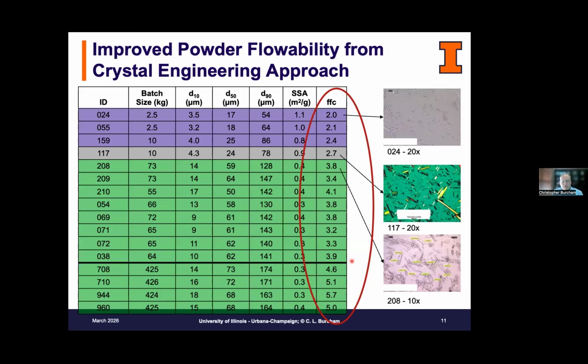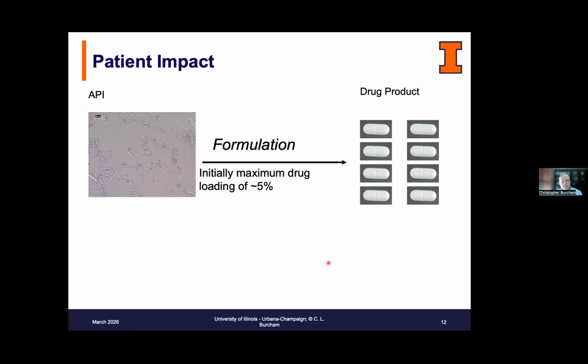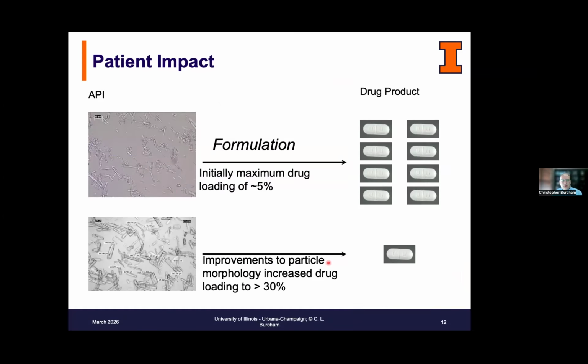So it was a great success. We were able to go from material that had poor aspect ratio and poor flowability to material that across a large number of scales had a much improved flowability. And when this work was initially done, we thought this was fantastic. This is a great model to carry forward. We're able to go from an impact on a patient where they'd have a high tablet burden to one where it would have a much lower tablet burden through the particle engineering efforts.